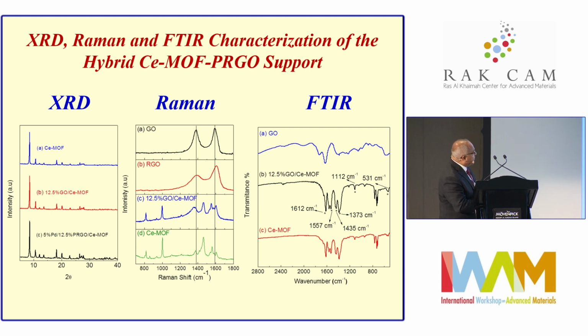The Raman spectrum also shows a combination of the cerium-MOF pattern and the reduced graphene oxide, because we're doing a reduction process here, and this all appears in the hybrid structure. All the peaks that belong to reduced graphene oxide and cerium-MOF appear in the hybrid structure. Similarly, FTIR shows the combination of the peaks related to graphene oxide and the peaks related to cerium-MOF in the hybrid structure. So we can say that we have the structure that we intended to form between these two types of support, the graphene oxide and the cerium-MOF.